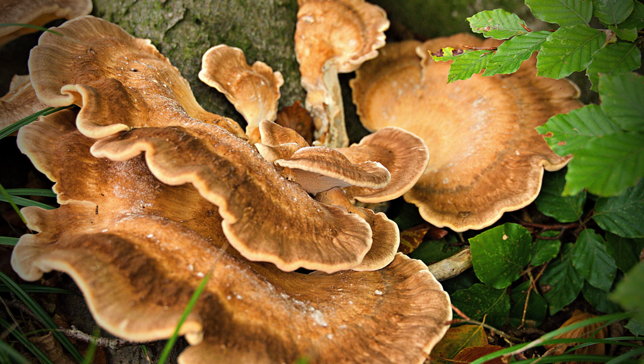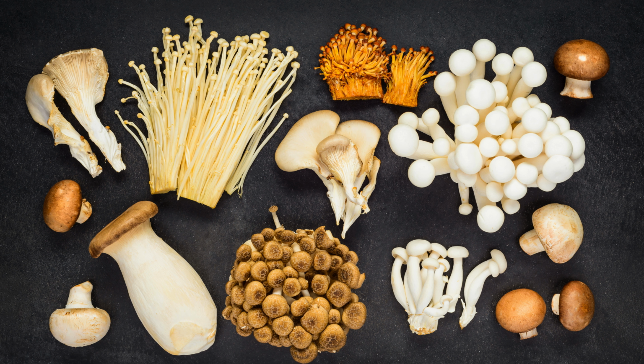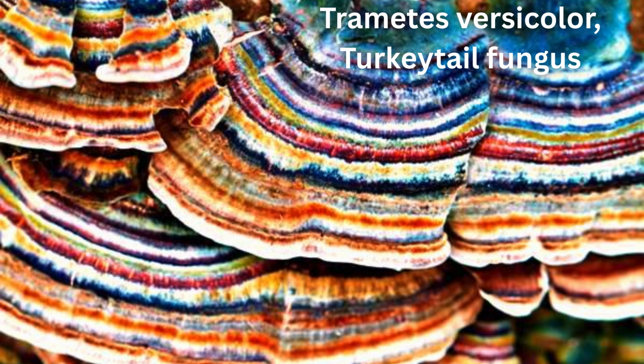Being xylophagous in nature, higher fungi practically utilize a wide variety of materials for their propagation, ranging from simple defined media to complex lignocellulosic biomass that are readily available. And it has been noted that in addition to the fermentation mode, the choice of the nutrient substrates can be used to tailor the mycelium material's properties for their use in various applications. For example, there was a significant variation in the moisture level of Trametes versicolor-derived biomaterials, with different agricultural residues as the feed substrates. Average moisture levels of 6.5% and 8.6% were recorded when grown on cotton and rapeseed straw, respectively.